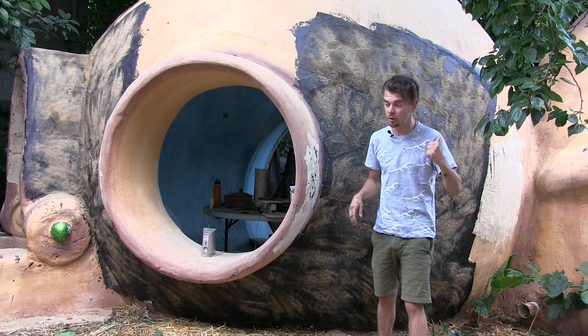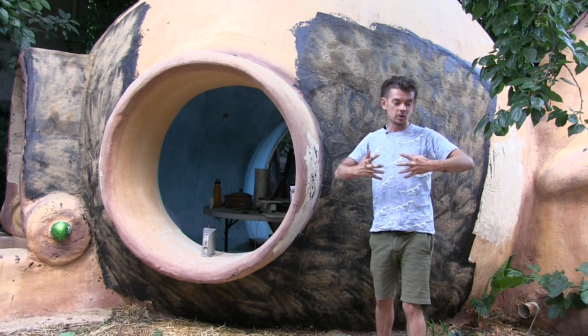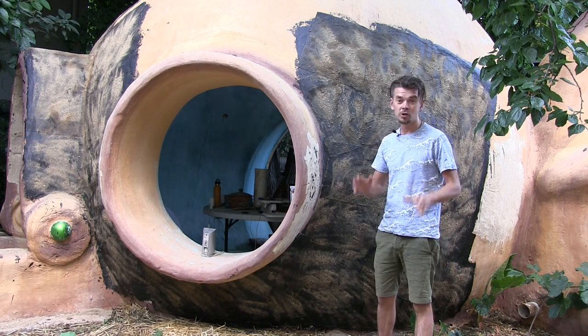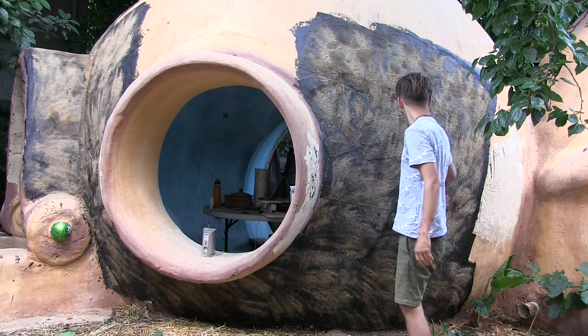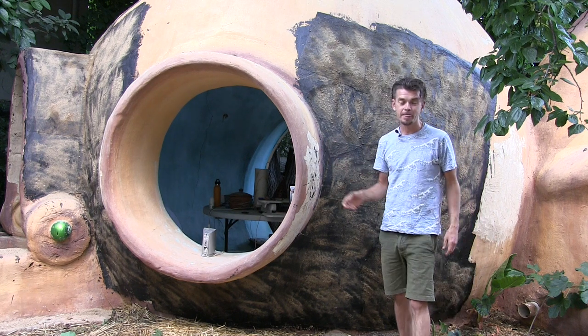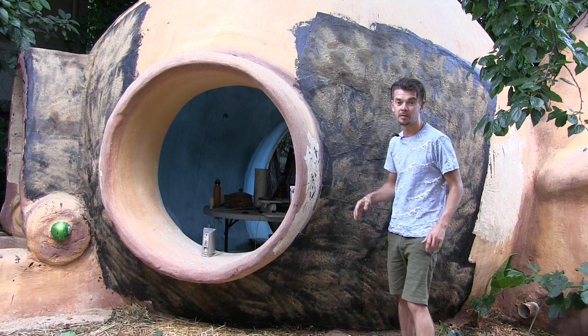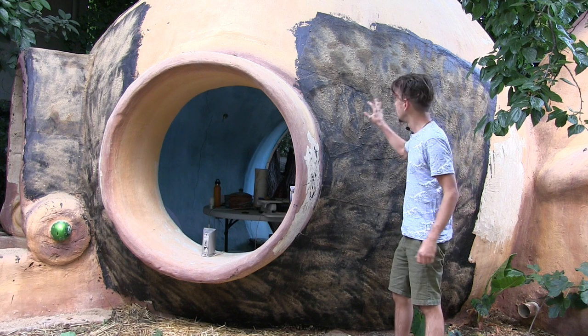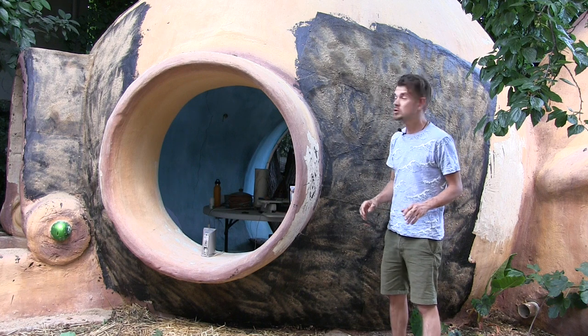It's all perfect on the sandbag dome, I'll show you now. But on an aircrete dome the water got in, the aircrete obviously swells up, caused some plaster to crack. So urgent waterproofing operation — we started by stripping whatever loose material was there, and then started to apply these squares dipped in bitumen, impregnated with the bitumen waterproofing material.